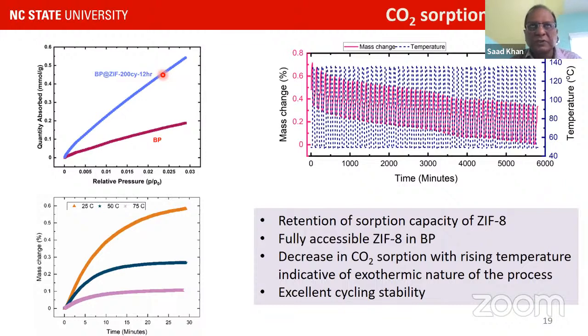So that's good. That's suggesting that the MOFs are not getting blocked in any way, and perhaps the banana paper structure is helping that. The second is actually a mixture of carbon dioxide and nitrogen, and we see that we have good absorption. And we actually see that the absorption goes down with temperature, suggesting the mechanism is an exothermic process. The numbers are pretty good. So again, it's a viable approach. And if you look at the cycling, we can do some nice cycling with temperature, showing reversibility. So it seems to show some good properties when we try to do CO2 absorption, just pure CO2 or CO2 from a flue gas.